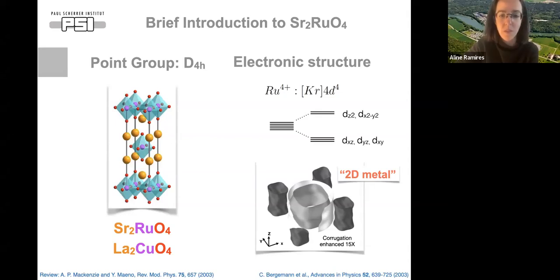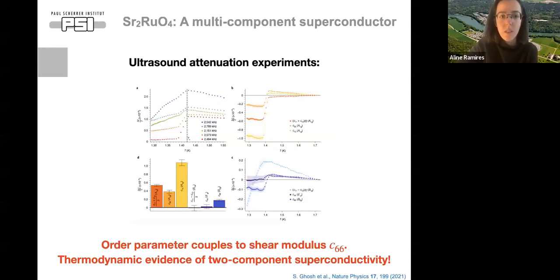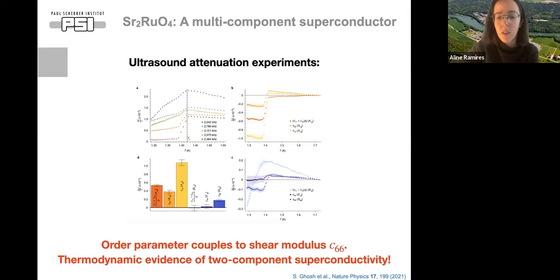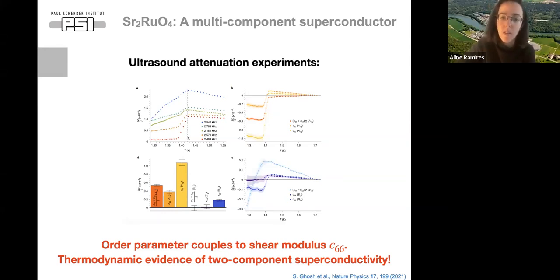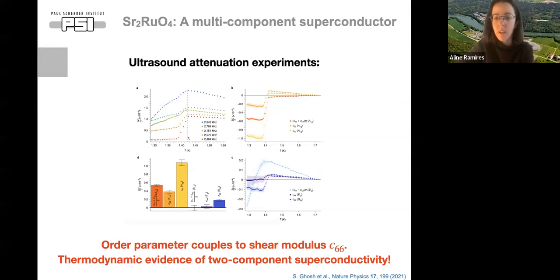These are the basic specifications of this material in the normal state. Now let me take you through some recent experimental developments, starting with ultrasound attenuation. This rather non-trivial experiment tells us which shear modulus can couple to the superconducting order parameter. What was striking was to see that the shear modulus C66 has a discontinuity at the superconducting transition temperature around 1.4 Kelvin, indicating that the superconducting order parameter has two components, and the product of their symmetries equals the B2g symmetry of C66.